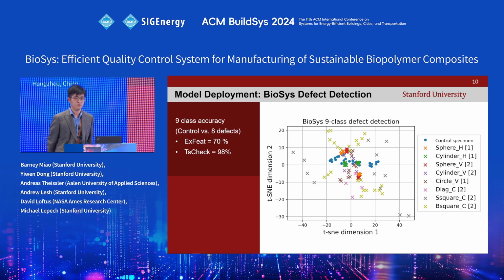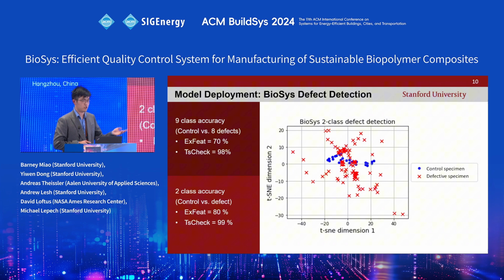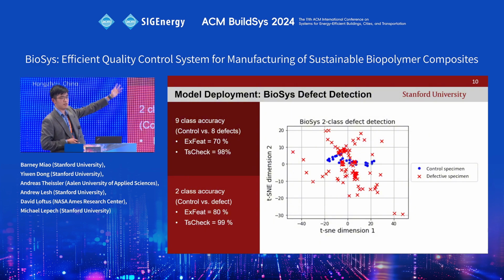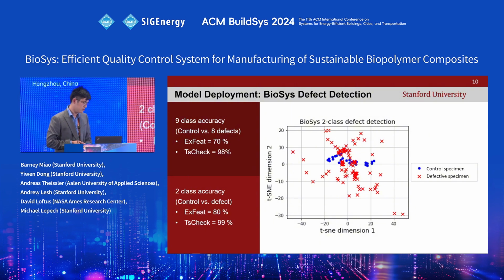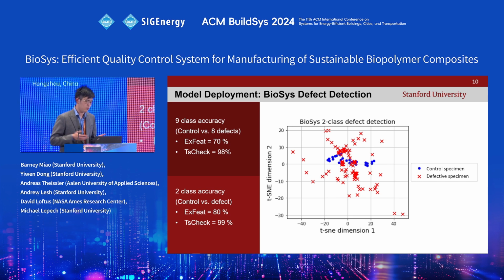If you didn't really care about what type of defect your specimen had, if you just wanted to know, is there an issue with my wet mix? You would have a two-class accuracy, so you just change all the previous X's into reds. And you can see here a clear distinguishment between a proper biopolymer composite and one with a simulated defect.